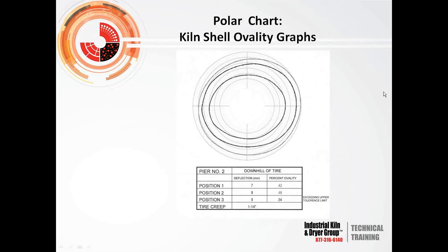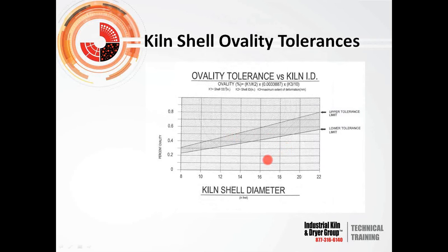And this is just an example of the charts we use for determining what the ovality is, and you have the 3 measurements here on the chart, and it'll give you a correlation of what is happening during the course of a revolution. And from our experience, we pretty well know what range that ovality meter should predict. Basically, there's a graph on here, a function of the diameter of the kiln or dryer, it doesn't really matter, and the percent ovality. So we pretty well know what acceptable range we have to stay within.